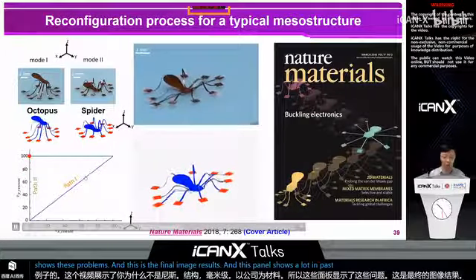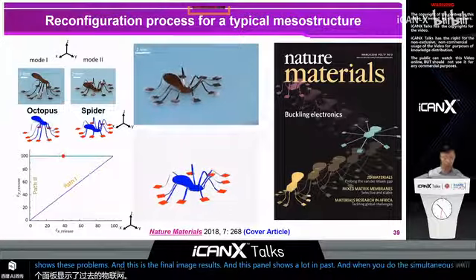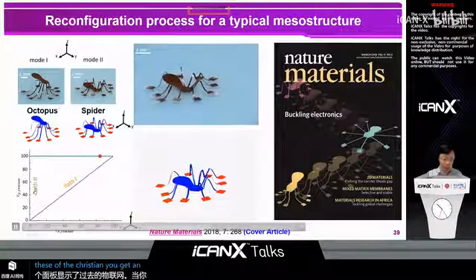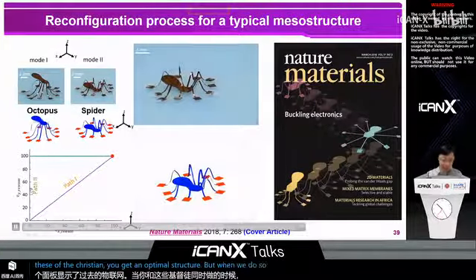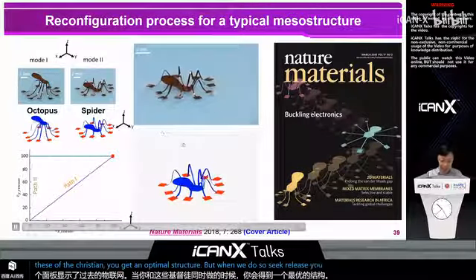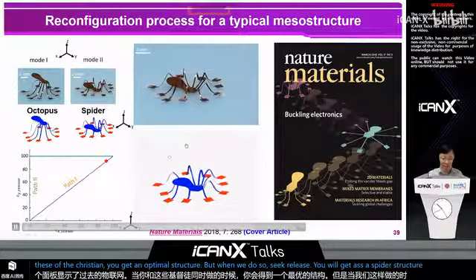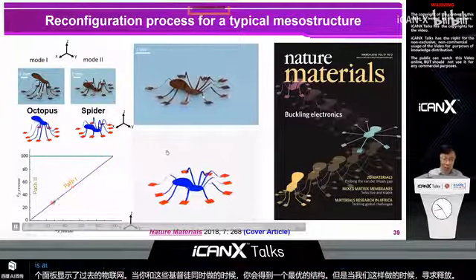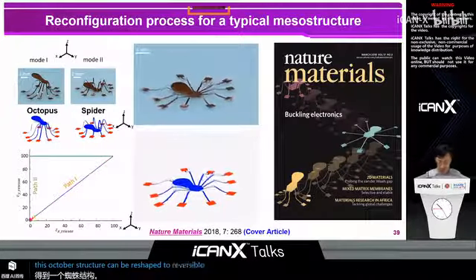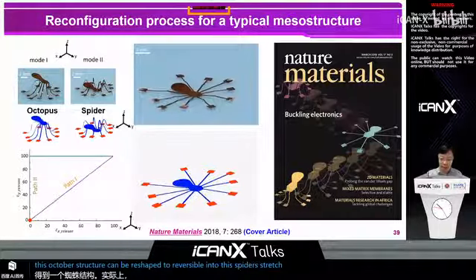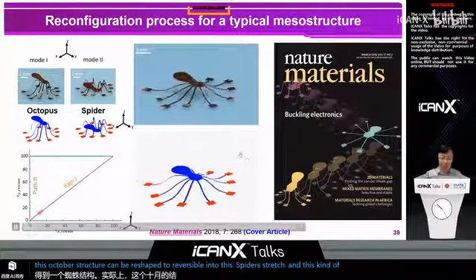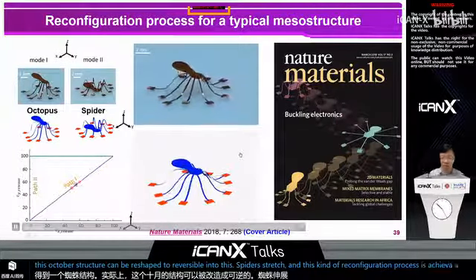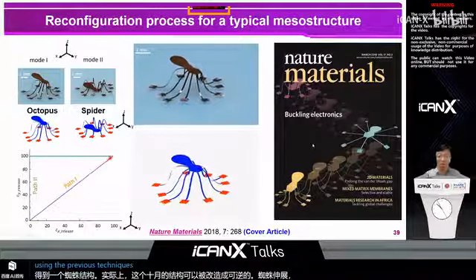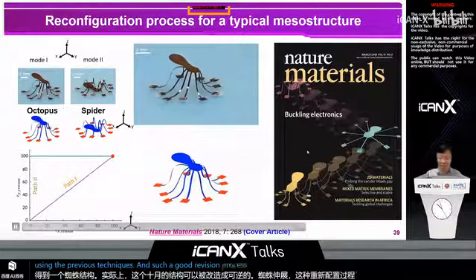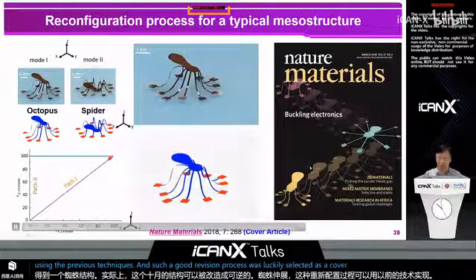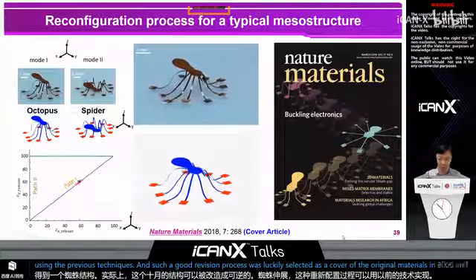When you do the simultaneous release of the pre-strain, you get an octopus structure. But when you do sequential release, you will get a spider structure. And actually, this octopus structure can be reshaped reversibly into this spider structure. This kind of reconfiguration process is unachievable using the previous techniques. And such a reconfiguration process was luckily selected as a cover of Nature Materials in 2018.